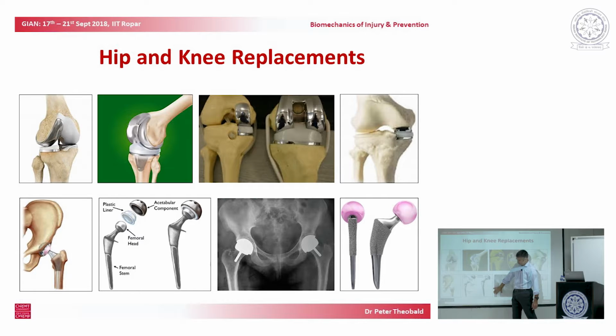You can, though, get breakdown of the PMMA cement. You can be at risk of not getting a uniform thickness of PMMA either side of the implant. And so much like any kind of DIY where you were trying to insert something blind into a cavity, you're reliant very much on the technique of the surgeon. You're very much reliant on the technique of the tradesman, were you to have a similar thing done outside of an operating theatre. And so there is risk of the PMMA cement-based route that the fracture doesn't set well or that the femoral stem doesn't set in the correct alignment. And it doesn't take much to realize that this is a very close, snug fit. If the femoral stem is in any way out of line, then you're going to get an increased stress, perhaps on the rim of the cup itself. Increased stress will relate to increased wear and premature failure of your implant.